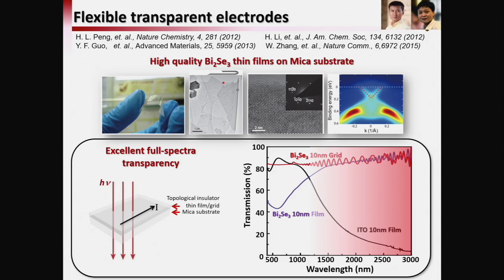And then what is this oscillation? This oscillation actually tells us that the thickness of the film is very homogeneous. This is interference from the reflection from the top and bottom surface. This helps us to determine the thickness. That's why we know it's 10 nanometers. All right, this is one example.